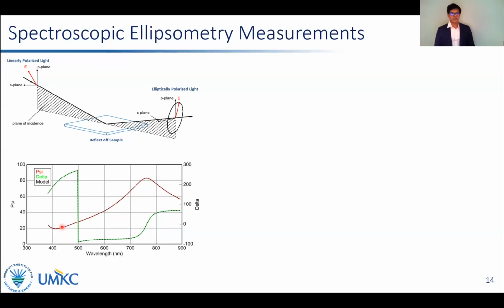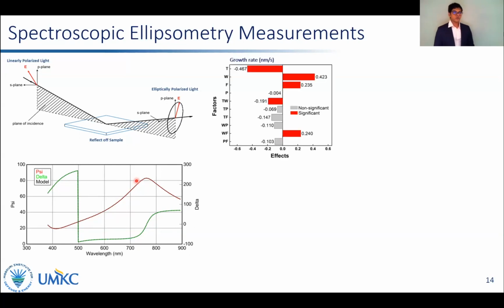A Cauchy model representing a transparent thin film on a silicon substrate was fitted to this experimental data to extract thickness and refractive indices of the films. The growth rate was then calculated by dividing the thickness by the deposition time for the film.